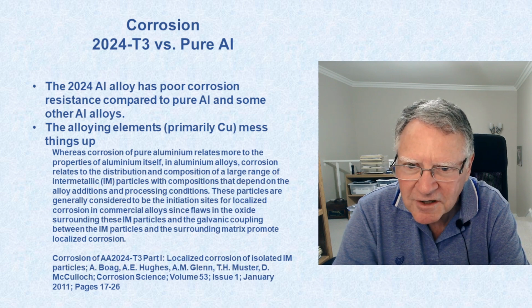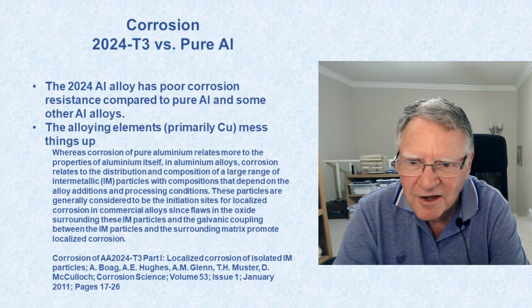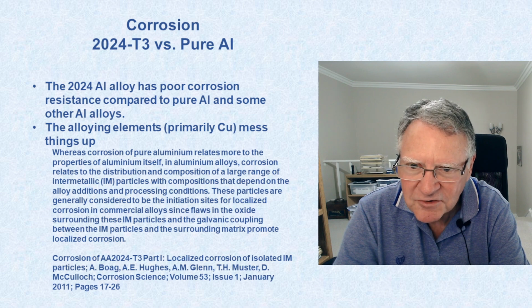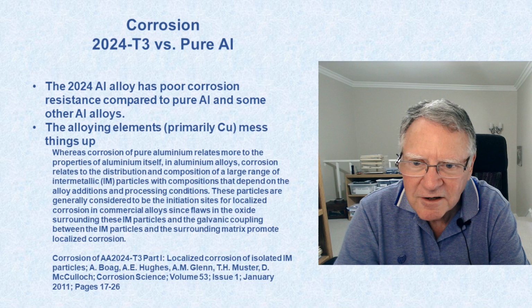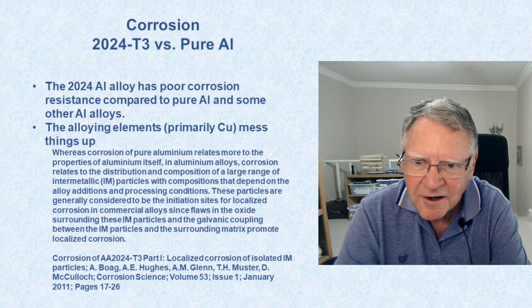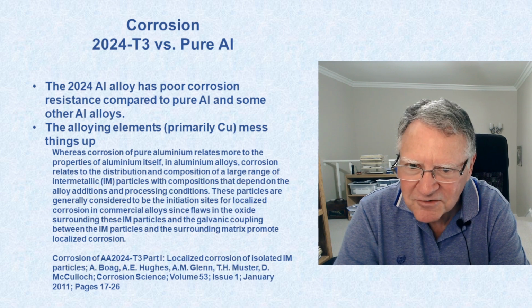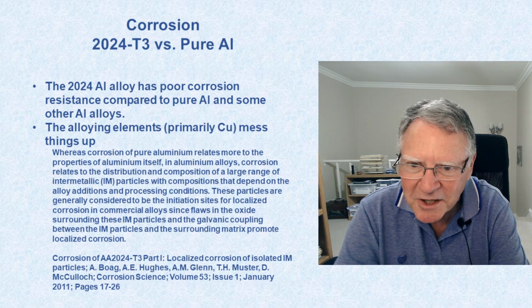We know that it's not just the copper, it's the copper near the surface. If you put a thin layer of pure aluminum on the surface, that will actually protect the material from corrosion. And in fact, this is what Vans uses. Their 2024 aluminum that they use for their skins has a very thin layer of pure aluminum on the surface to protect it from corrosion. This is not something that Vans does. They buy it from a very large aluminum manufacturer, and the manufacturer is the one that actually puts the aluminum cladding on the surface.